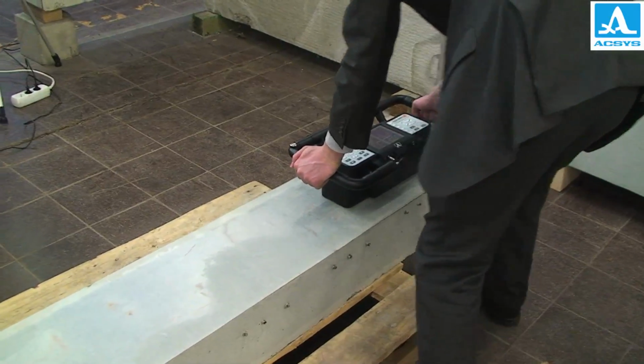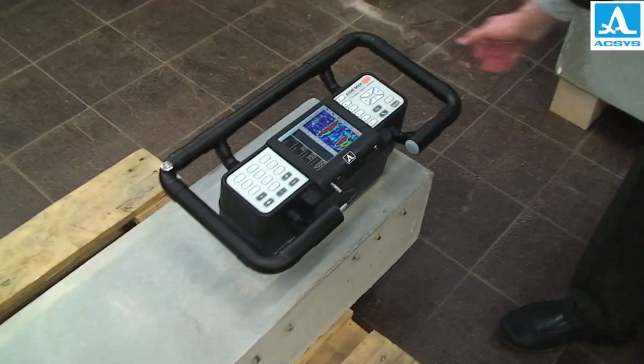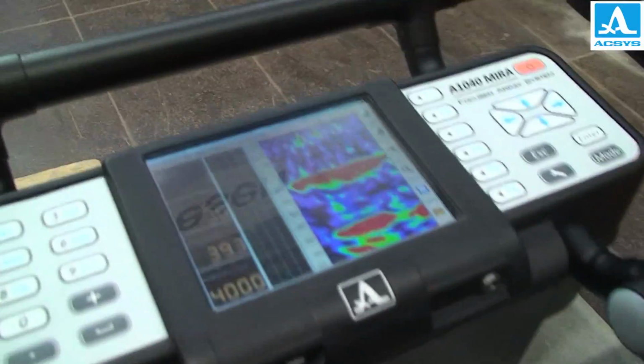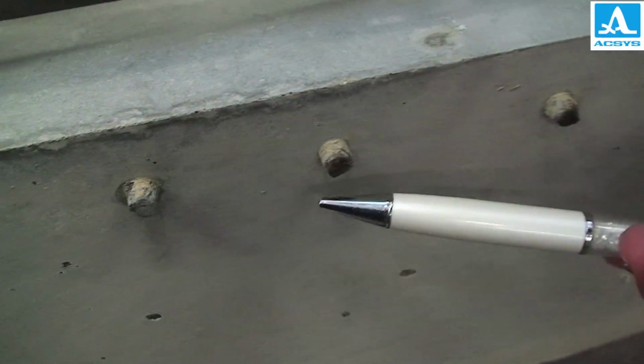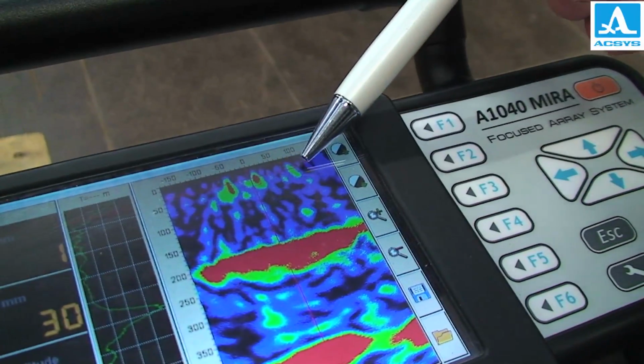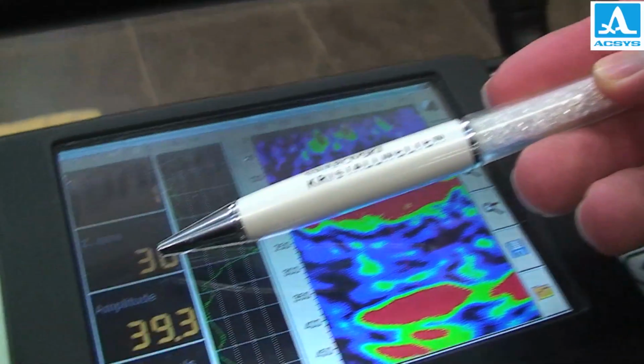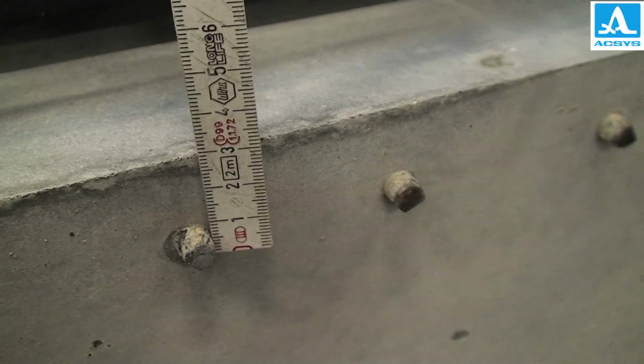The next tomogram shows the location of the next set of bars at about 30 millimeters from the top of the slab. Physical measurement taken at the edge of the concrete sample confirmed these findings.